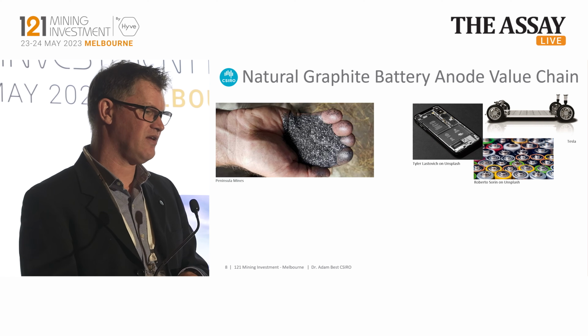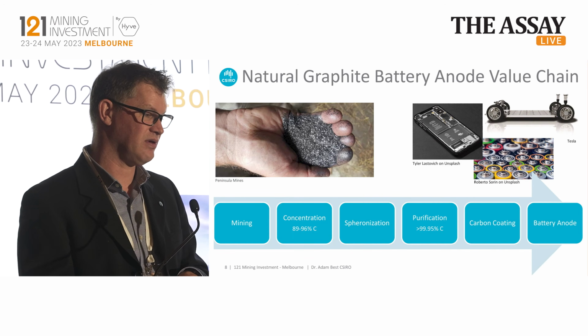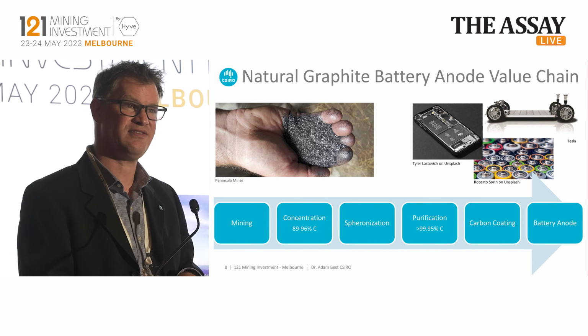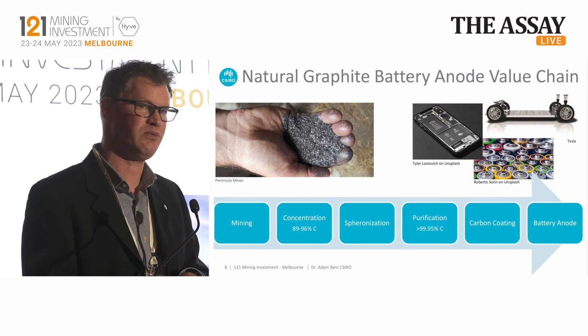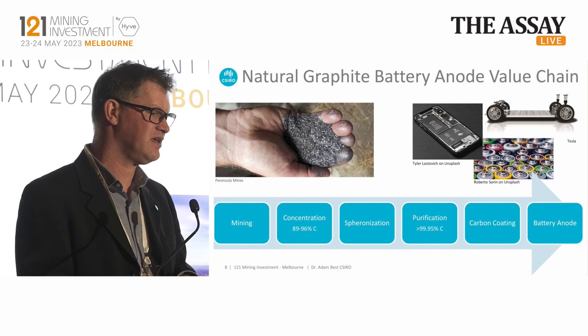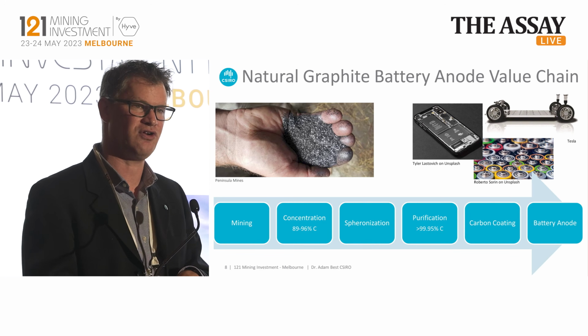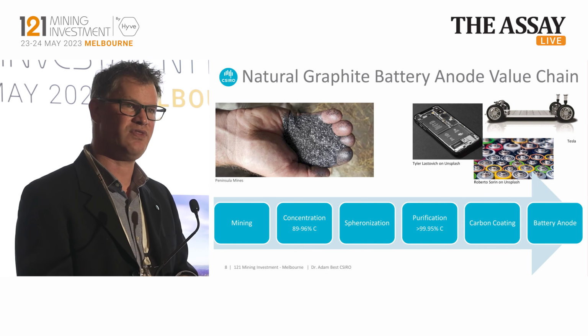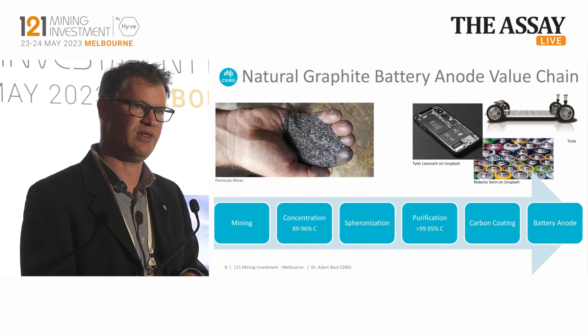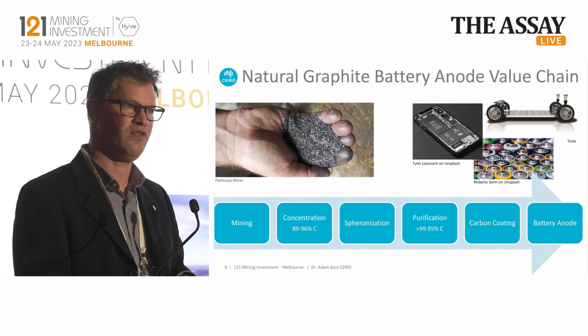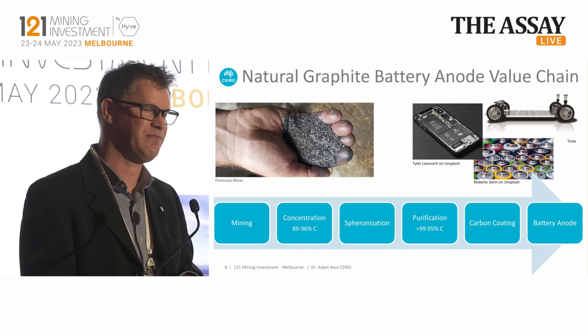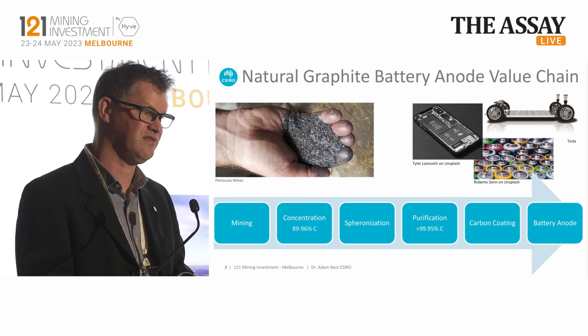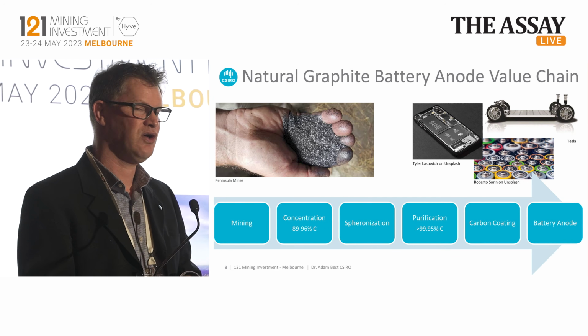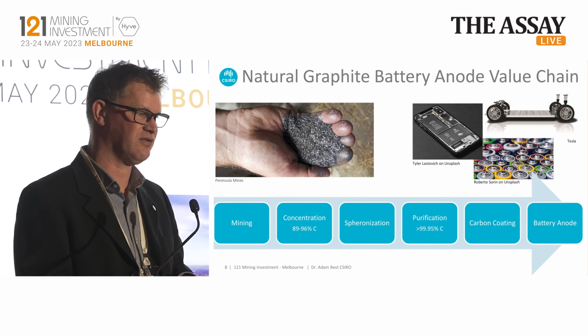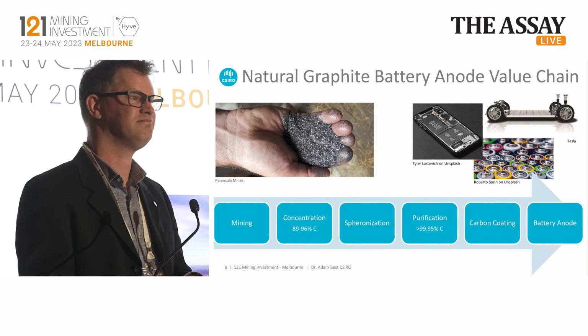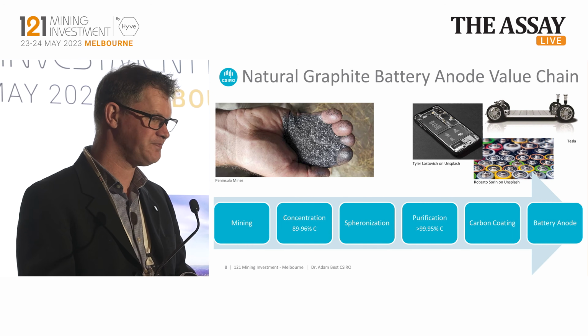So the natural battery graphite anode chain is quite a long one. It obviously starts at discovery, but we'll ignore that for the moment, but we'll think about first mining. And the first thing that we do once we mine that graphite is we need to concentrate it. We need to get rid of the majority of the impurity matrix that the graphite sits in. So depending on the grade of graphite, that can run from 3% graphite in some Chinese mines, also in some Australian mines, all the way up to 25, even 30% graphite. Obviously, the higher graphite content, the better value you're going to get from your mine side.